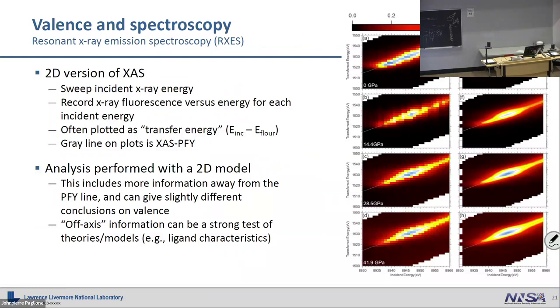This is what you would get for more of the HERFD or the RIXS spectra. These are particularly good for things that are more like transition metals or basically not rare earths, where you don't have the same kind of splitting and you want to try and resolve the peaks a little bit better. And so this one I think is uranium antimony 2 that we're looking at in this case. And so rather than seeing two distinct peaks, you can see two hot spots as you go through some of these things. And so this is just a different way of getting the same information from the measurements.